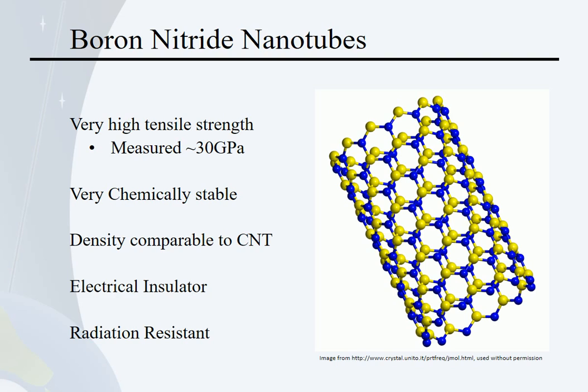The strength is a little bit less, about 30 GPa, so not amazing, but boron nitride is a relatively new material, and theoretically, it should be comparable to nanotubes in terms of strength. So this may simply represent the earlier phase of research we're in. Beyond that, though, there are some very important differences when compared to nanotubes.